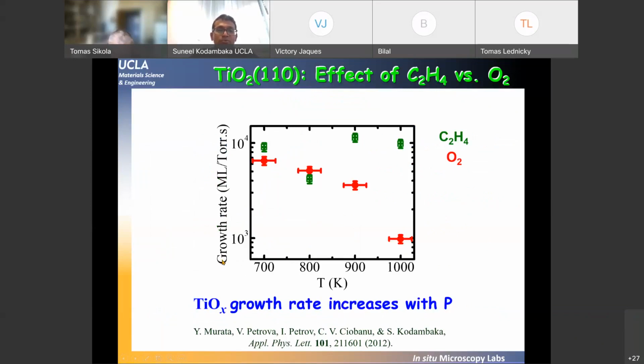And here is the summary of those experiments. So this is the growth rate of the stripe phase, and this is normalized to the dose of a given gas. And here the red symbols correspond to the exposure to oxygen at different temperatures, and the green symbols correspond to the exposure to ethylene. But what is not said here is that it's not pure ethylene, but there is a background, small traces of oxygen as well. So it's ethylene with small traces of oxygen.